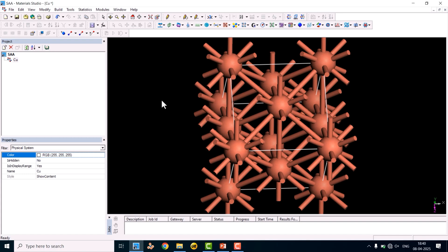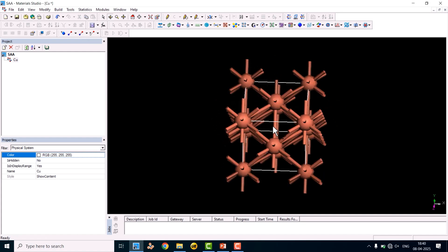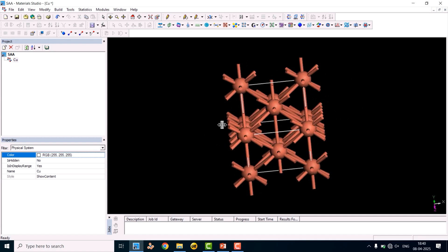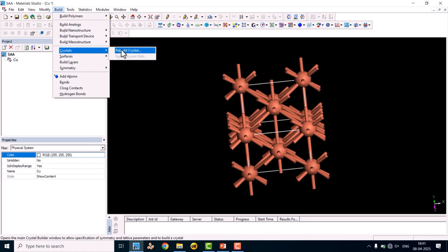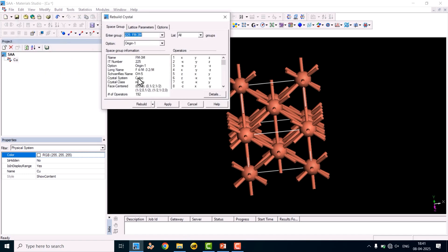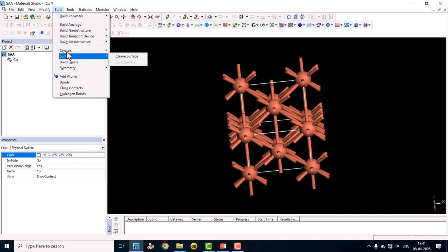Close the dialog. Now we can make the copper 1,1,1 surface single atom alloy catalyst. This is the bulk structure of copper — face-centered cubic, FCC. Go to Build, then Crystals, and click Rebuild Crystal to see the space group and other parameters. This is FM3M, space group 225 — the cubic structure. Now to create the 1,1,1 surface, close that dialog, go to Build, click Surface, and select Cleave Surface. In the Cleave Surface dialog, enter the cleave plane as 1, 1, 1 — replacing the zeros.